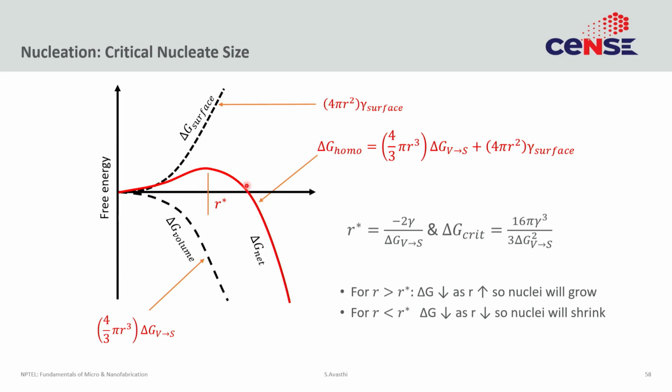But since we are doing a chemical reaction, at some point this must be initiated by just one molecule. This has to be initiated at some point. You can't directly make a very large nucleus. So, then how does that work? Whenever you start the nucleation process, there is a certain barrier. You do not immediately form a nucleus. What must happen is that the small nuclei keep forming and desorbing, there is this dynamic equilibrium, but that equilibrium is slightly biased towards formation.